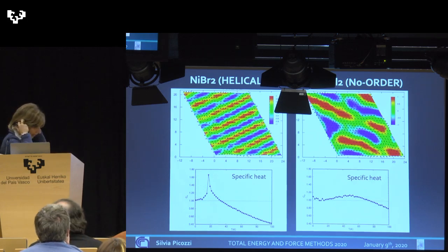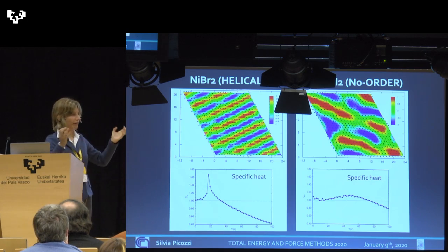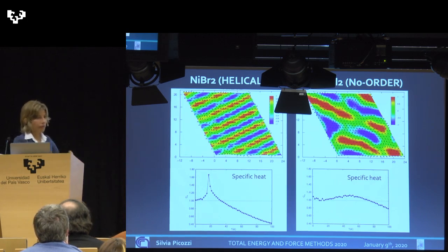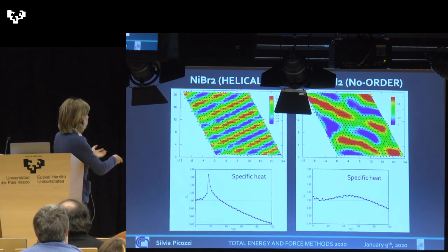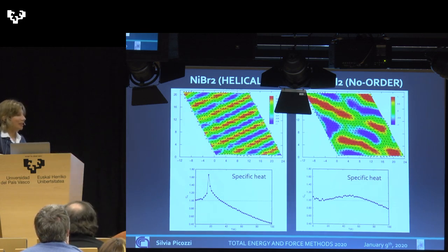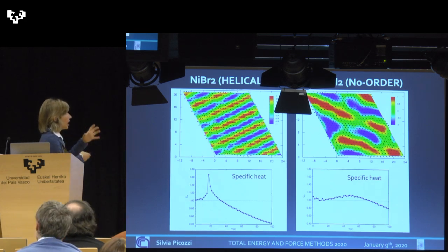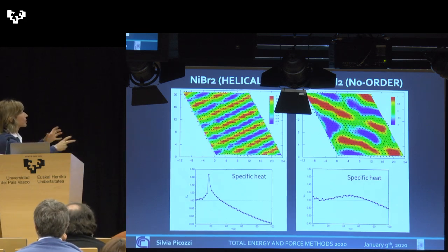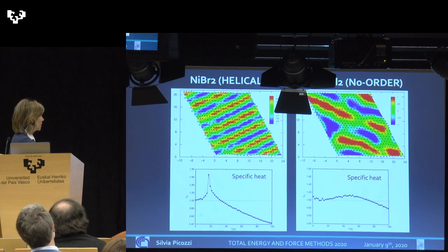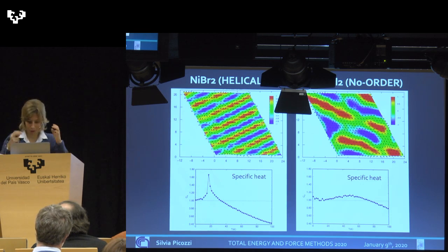In chloride, basically the spin-orbit is 0, right? So you don't have any source of anisotropy. And in fact, it doesn't order. If you calculate specific heat, it's basically flat. Or it orders, I mean, it's not completely forbidden. In principle, it could order because of frustration. But we don't see a clear sign of ordering. Whereas in nickel bromide, you really see a very strong transition. Temperatures are quite low, of course, 20, 30 Kelvin.